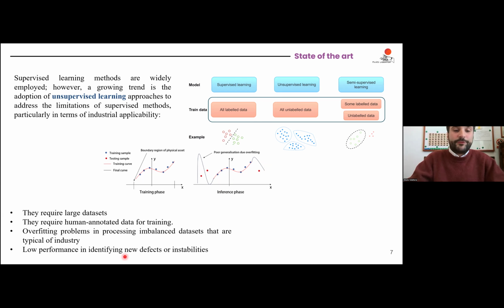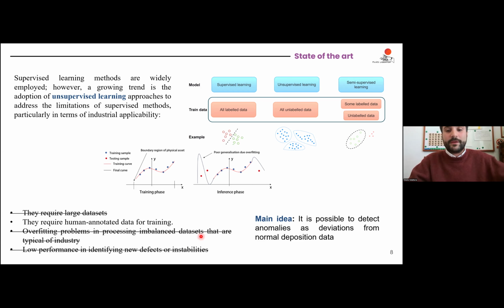So this means that if you are getting a new defect that you didn't take into account during the data collection, or an instability that happened in a different way with respect to what you observed, you are not able to detect it. Indeed, when you use unsupervised learning, you do not have to deal with this problem, because the main idea here is that it is possible to detect anomalies as deviations from the normal deposition data. So the only thing that you need is normal deposition data.